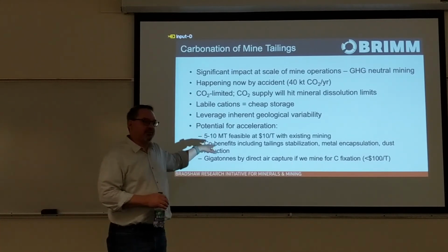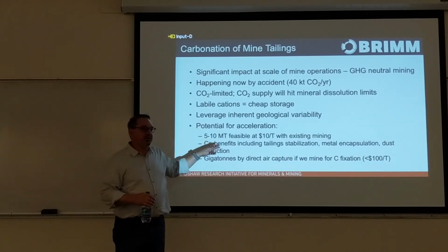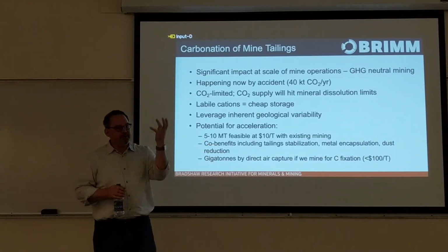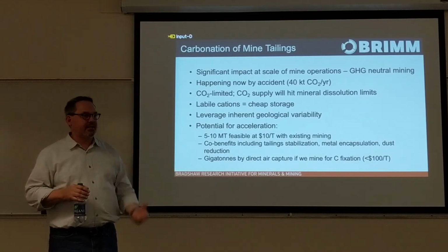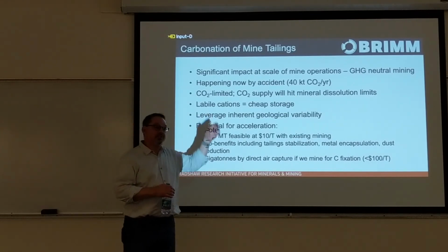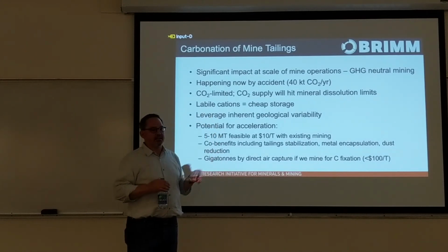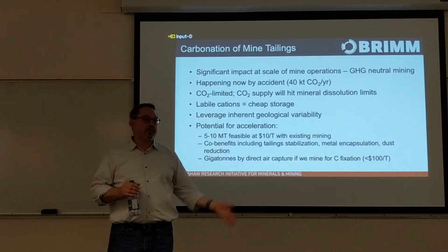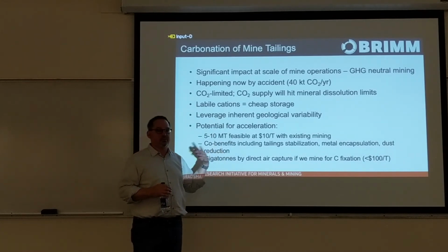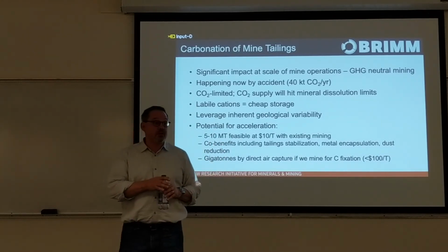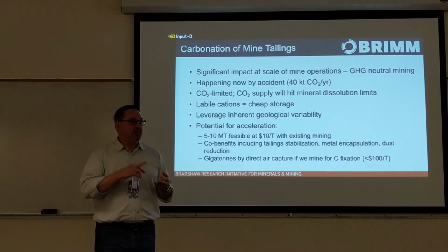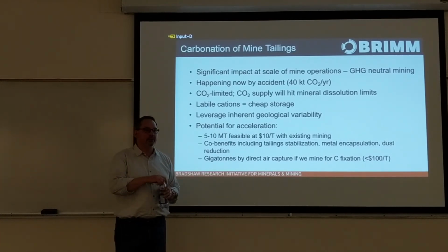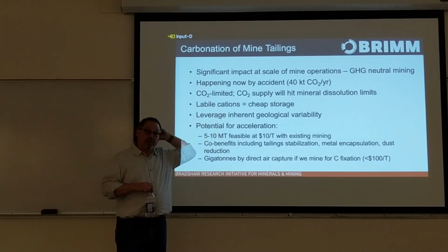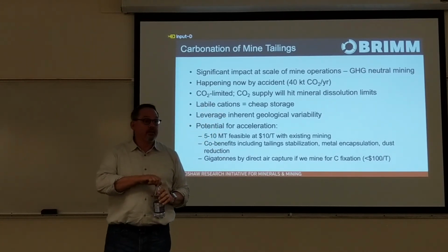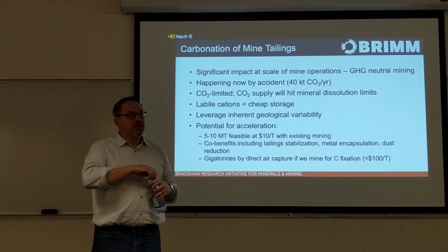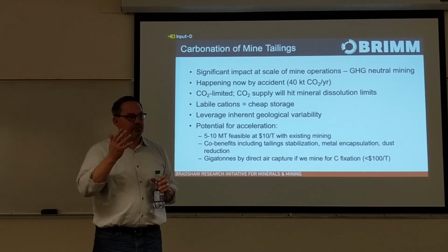When that same column has 60% pore saturation, it comes through faster because now you create pipeline. You have so much water present that the gas channels into little chimneys. And those chimneys then mean that a lot of the tailings don't react. And if you have too little water, you don't get any reaction because we need water for the reactions. Maintaining water content is also another factor. So reactivity of the tailings, water content, permeability, flow rate will all affect that. But to go 100 hours with no detectable CO2 at the top was significant. And all that CO2 ended up in minerals.